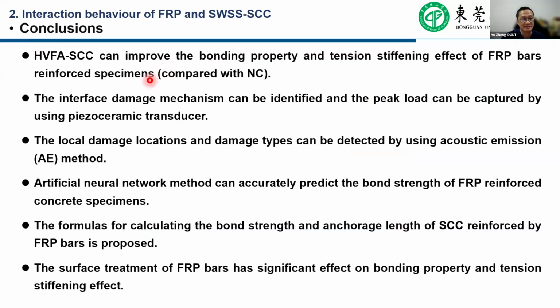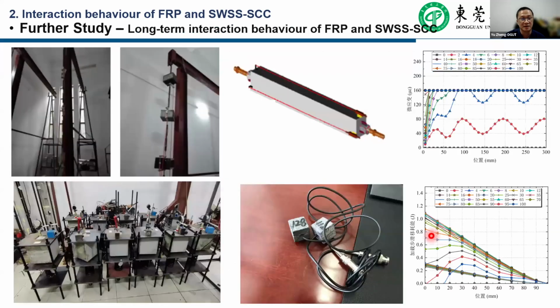Finally, in this stage, we get some conclusions: the self-compacting concrete improved the bond behavior, and in bond, the damage mechanism can be identified using the piezoelectric transducer, and the local damage location can be identified using the AE method. The ANN method can accurately predict the bond strength with a database with a lot of specimens. And the formulas for calculating the bond strength and anchorage length for the FRP reinforced self-compacting concrete are proposed. In further study, we will try to study the long-term behavior of the FRP and seawater and sea-sand self-compacting concrete.